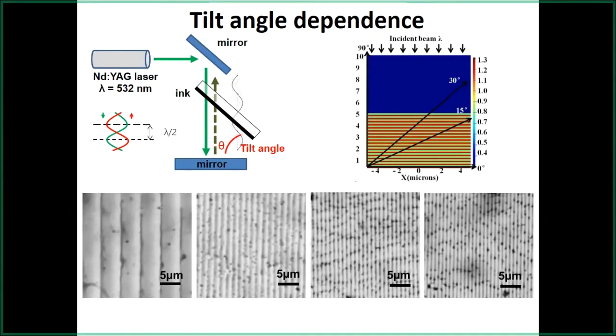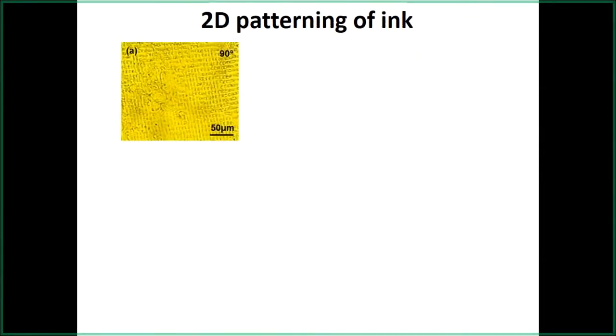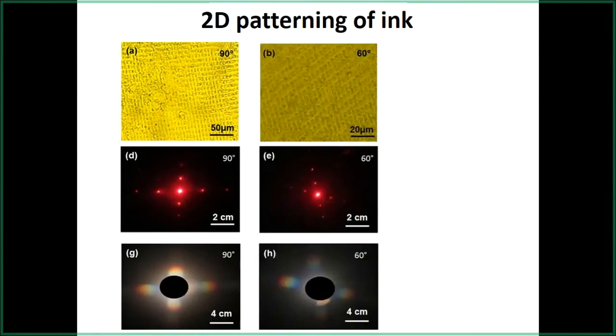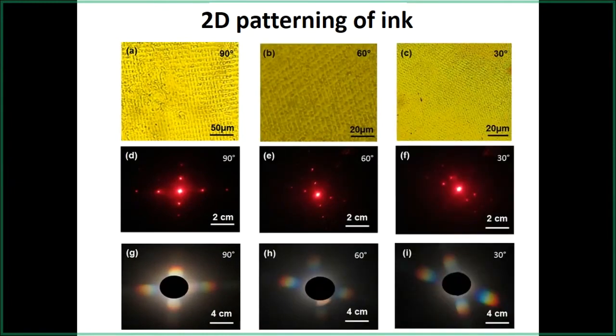Using the same setup, and using the same material, which is ink that absorbs green color, you can produce structures from several microns to submicron structures as well. So you can make these one-dimensional gratings by changing the tilt angle. Apart from the tilt angle, there are some other parameters, for example, the number of exposures you do. So we can also make two-dimensional structures. These are not the best images we got for these, but these are square-shaped periodic structures.